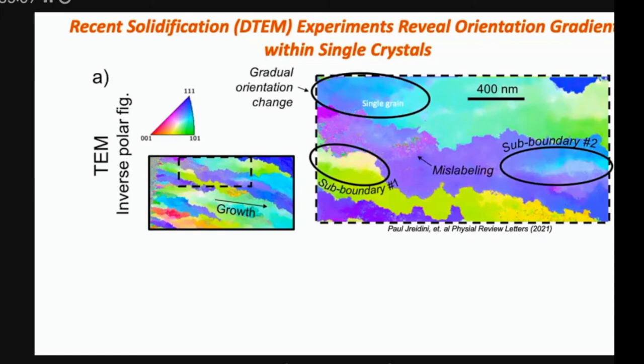And what they saw was something that's very non-typical for solidification. These colors represent roughly different grain orientations. But what you'll notice within a given grain, so look at the circles, you'll see changes of orientation within a crystal itself, which is very, very atypical. If you take any cast sample solidified, you'll see multiple grains, but within a grain the orientation is deadlocked. It's very rare that it rotates within a grain. What you see here is you see within a grain the color hue changes, indicating that somehow orientation has changed while solidifying within a single grain.